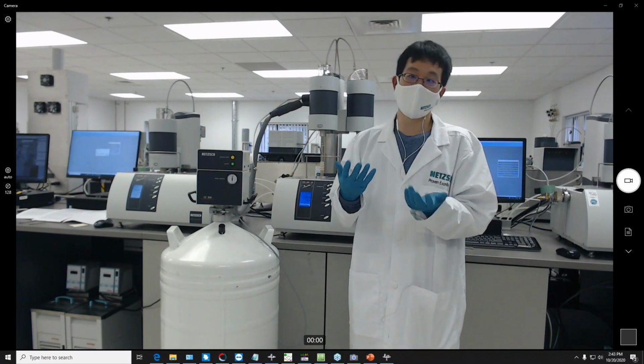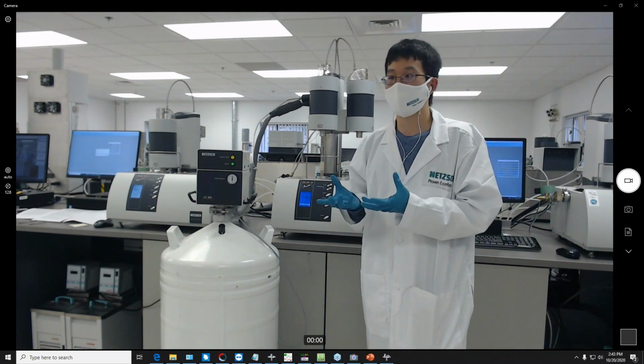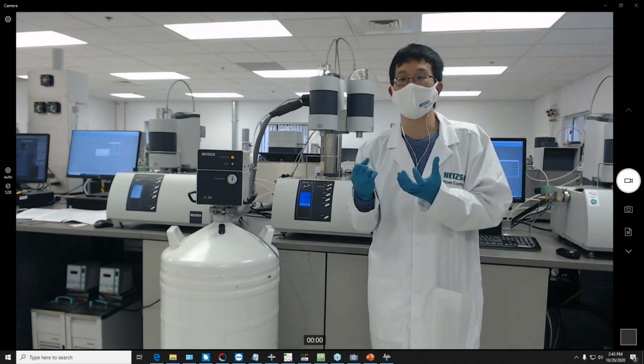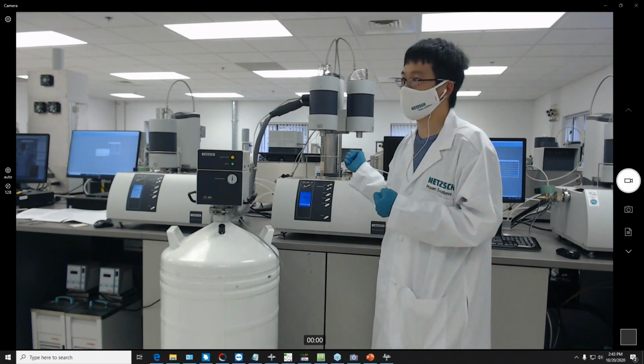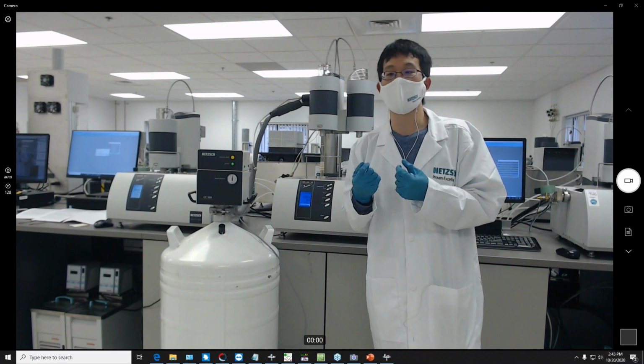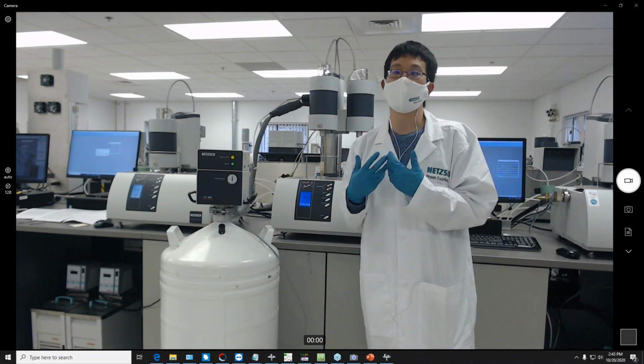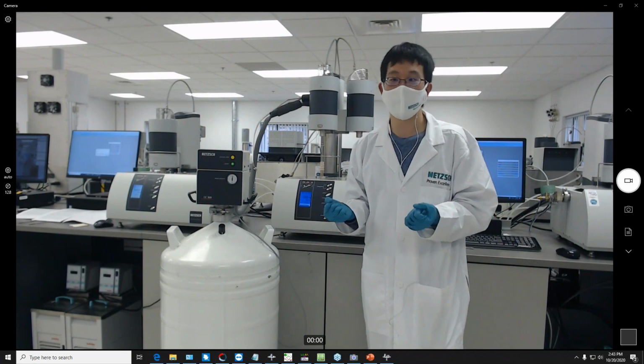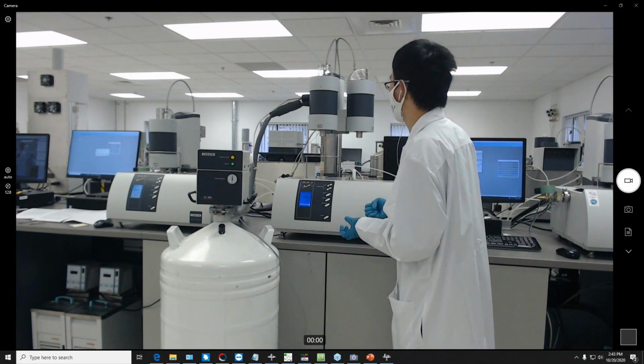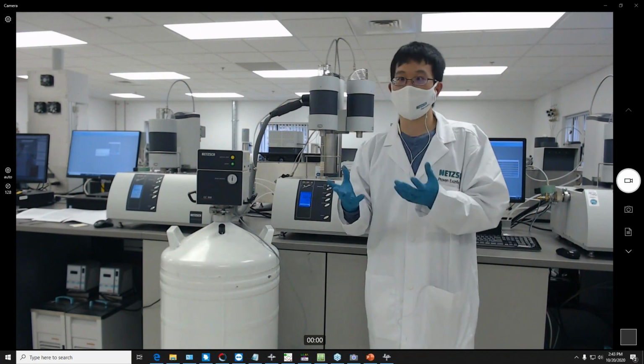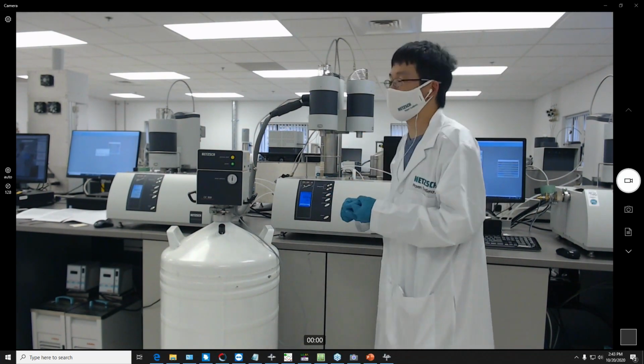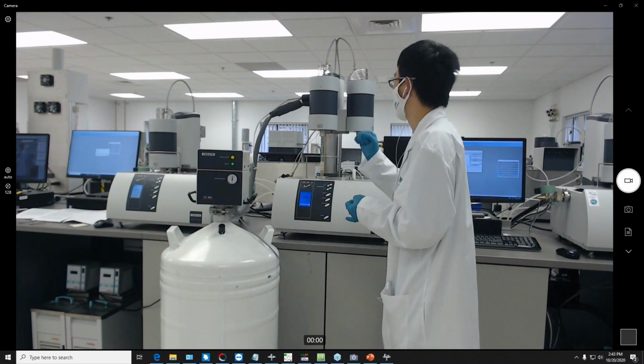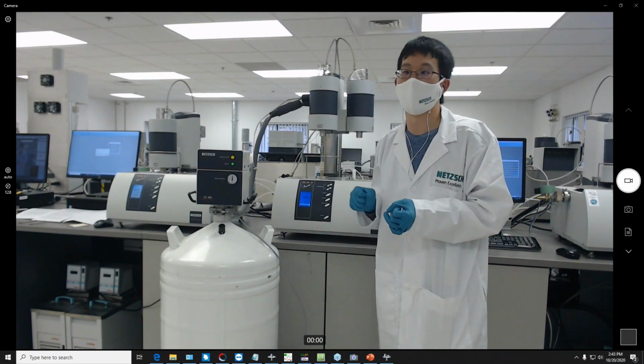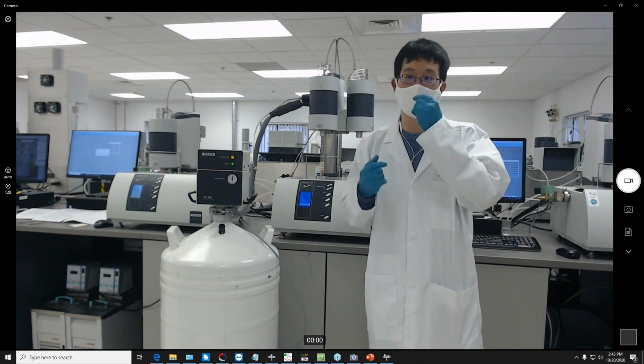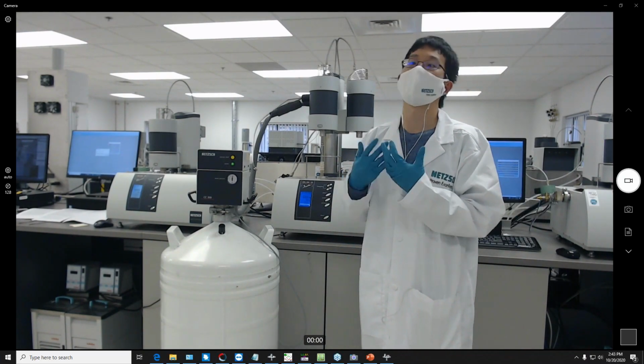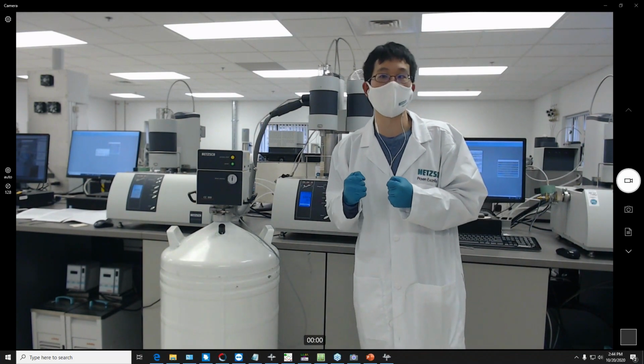If you lower the flow rates, you'll have a higher concentration of gas, so you have less dilution of your sample evolved gases, which might be handy if you're dealing with very small quantities and using evolved gas analyzers to try to identify them. If you use higher flow rates, if you have very reactive gases that could potentially damage the sensors or the protective lining of your furnace, then using higher flow rates will dilute those to have less impact and less possible interactions with those.